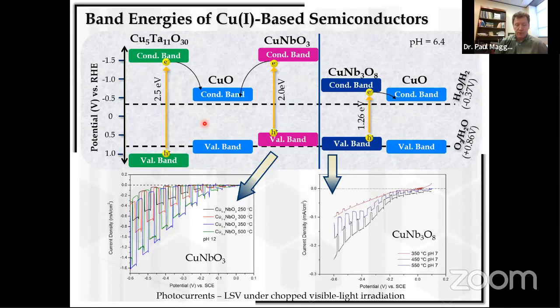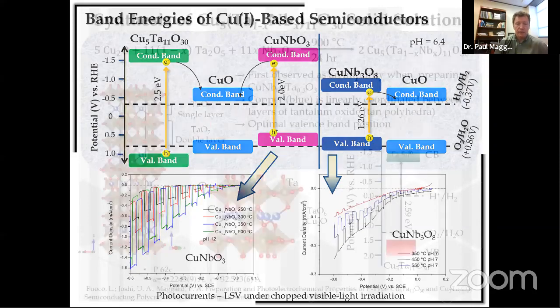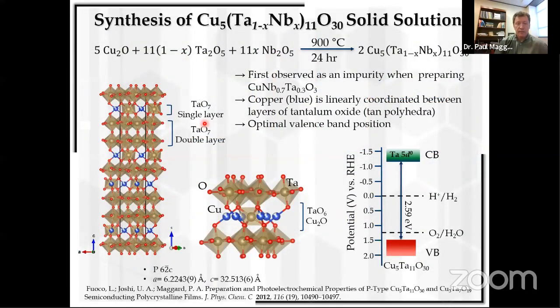Rather, we've looked for alternative means of driving this charge separation without the copper oxide islands, and that could lead to higher stability. And in particular, what we've looked at are solid solutions. And so solid solutions are mixing two elements onto one crystallographic site.